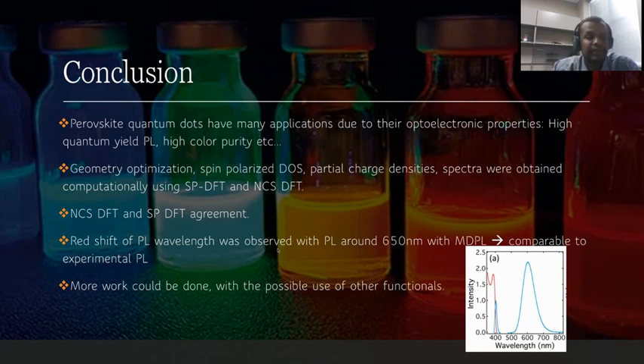But yes, we also saw the agreement between the spin-polarized calculations and the non-collinear spin calculations. We saw the redshift of the PL around 500 to 700 nanometers, and this is comparable to experimental values obtained as well. And like Dr. Kilin just mentioned, more work could be done by changing the cell size, and possibly other things can also be explored. Thank you for listening.